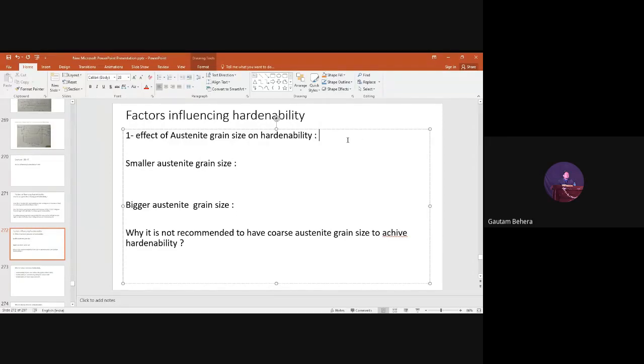So, how does austenite grain size affect this? Basically, we can have smaller austenite grains, or bigger, or you can write coarser, austenite grains. If we have smaller austenite grains, the hardenability will be poor. But if we have coarser, bigger austenite grains, we have good hardenability, or high hardenability. Good or high, you can write.